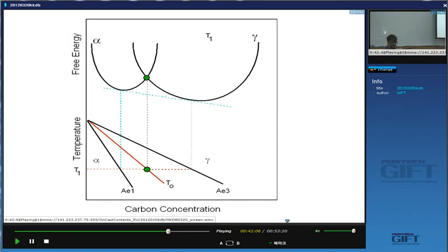So, if you have Thermo-Calc or MTDATA data and so on, you can obtain these free energy curves from that software. Yeah, are you familiar with that, roughly? Yeah. If I then draw a common tangent to these two curves, that gives me the equilibrium composition of austenite and of ferrite at a particular temperature T1 for which these free energy curves are calculated or measured.